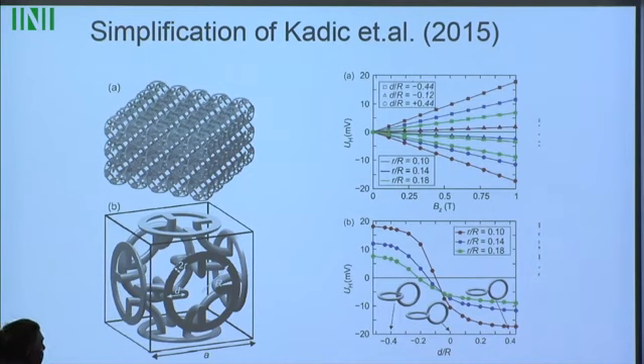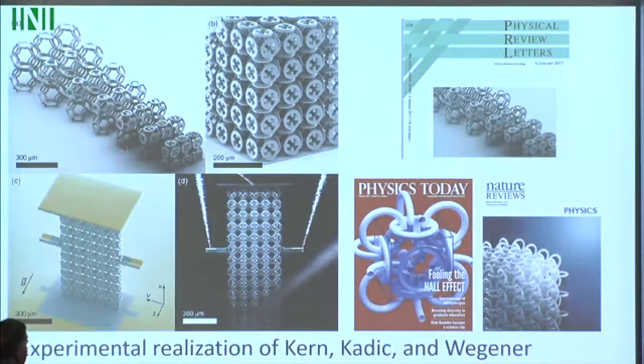And then, sure enough, one actually sees this sort of reversal of the Hall voltage. What's really remarkable is that Martin Wegener's group actually went ahead and built this, using a 3-dimensional lithography technique. Here you've got this interlocking ring structure. They built it, tested it, and verified that it actually had opposite Hall coefficient. I went to their lab and asked if I could see this. I was expecting something reasonable, but it's actually about the size of the whisker on your chin, maybe after you've had a shave. It's really quite tiny, but it was enough to demonstrate the effect.